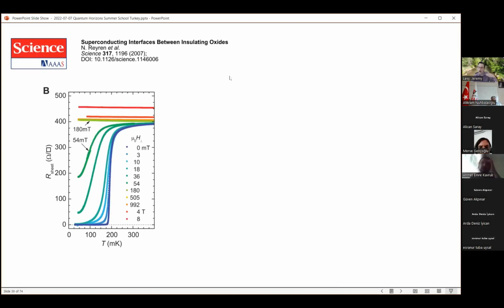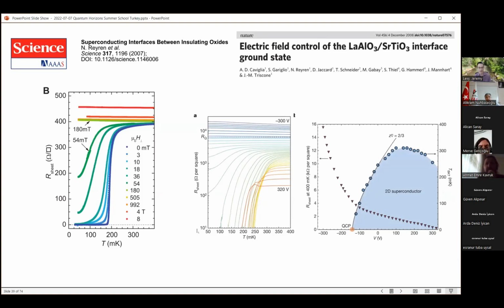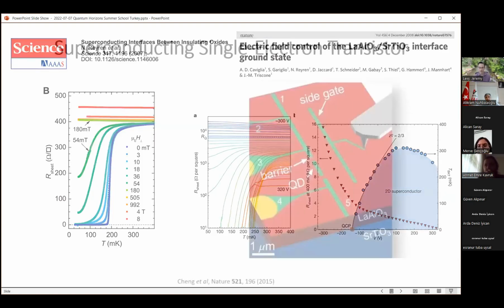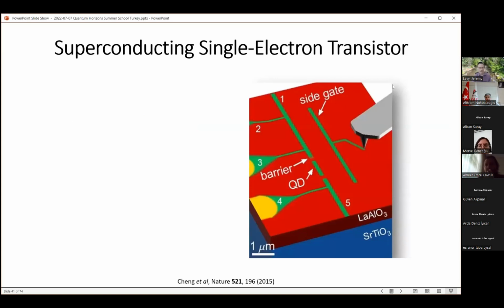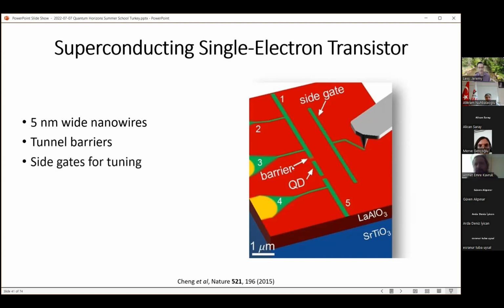More recently, with these oxide interfaces, it was rediscovered or reinvigorated this investigation of superconductivity, because now you can dope the system electrostatically rather than just chemically. People have observed superconducting domes that were tuned not by changing the doping density, but by changing the gate voltage. So we were interested in the general phenomenon of superconductivity, but we also wanted to make nanoscale devices. So we were interested in this particular type of device, which is called a single electron transistor. And it's made from these 5 nanometer wide nanowires, tunnel barriers, and gates, and so forth.